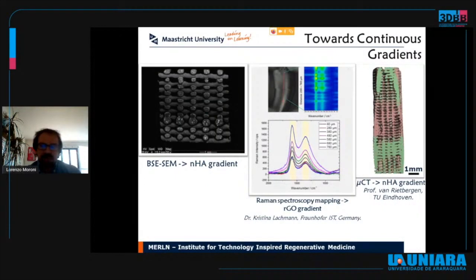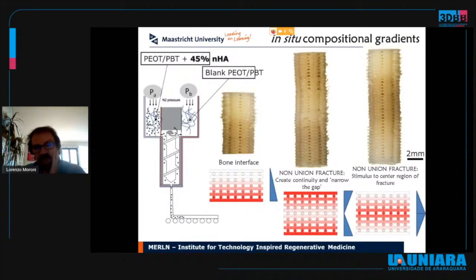We also use different kinds of characterization tools, from backscattering electron microscopy to Raman spectroscopy and micro-CT, to really evaluate whether the gradients are continuously changing throughout the scaffolds, and have then tested these scaffolds both in vitro as well as in vivo. Here you see the fabrication of a critical size defect, representing a non-union fracture in a rabbit model, where we chose two kinds of gradients, either mimicking the continuity on the bony stumps of the non-union fracture, therefore having there the highest amount of hydroxyapatite, or simulating a sort of callus region with the highest amount of nano-hydroxyapatite in the center of the construct.